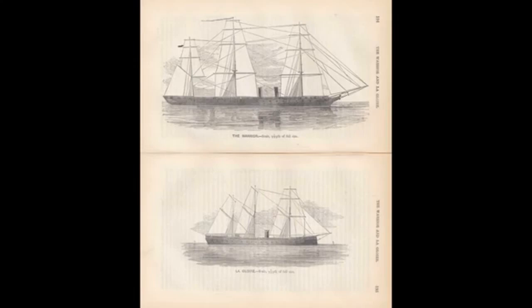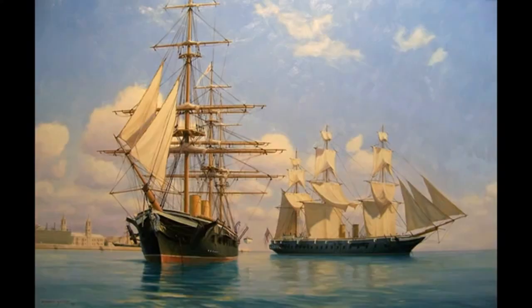Material quality was also important. Gloire's plates were 0.2 of an inch thicker than Warrior's, but gunnery tests by both parties showed that Warrior's plate was manufactured of superior material, as it took less damage when resisting the same shot.